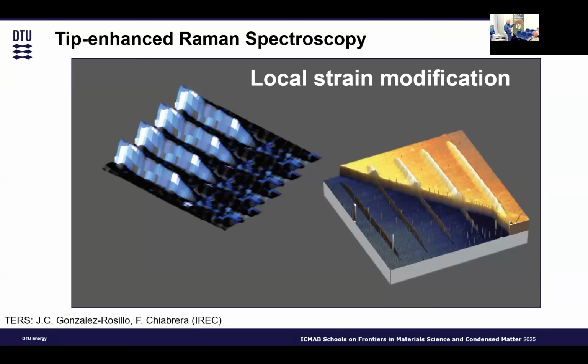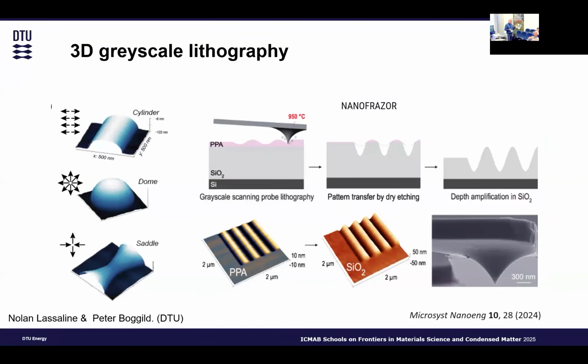We tried to measure with the PFM. It was impossible for us to detect any response from it. We think it's too weak. 1% is very difficult to see. So we are still looking at this structure, but we moved a little bit further. We asked ourselves, can we make it even higher? I mean, we need higher strain. If we want to really clearly see, we need to go to higher strain.